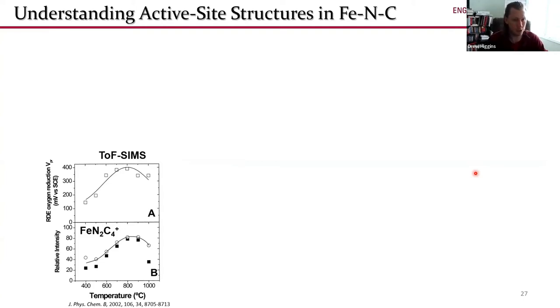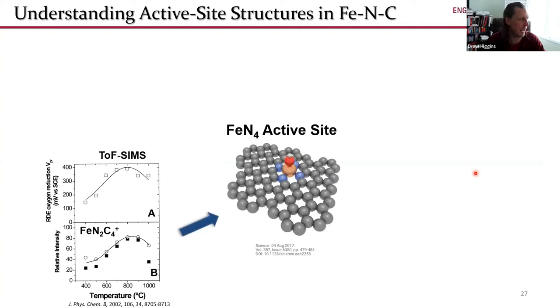But going back to 2002, that was the first compelling study that really pointed to the presence of these iron nitrogen carbon sites in the catalyst. And this was done by a technique called time of flight secondary ion mass spectroscopy. Essentially, you bombard a material and collect all these ion fragments that are coming off it. What these authors found is that they had these iron nitrogen carbon coordinated ion fragments coming off of their catalyst that they attributed to be from the active site structures in these materials. So that was the first compelling evidence of these species in these catalysts.